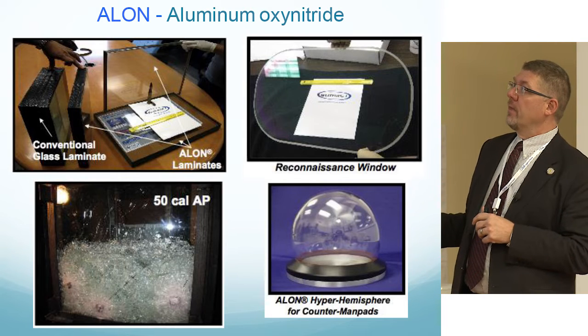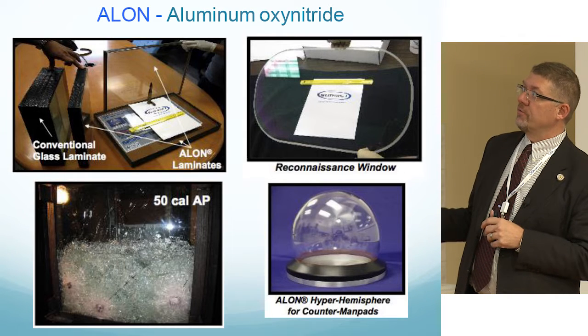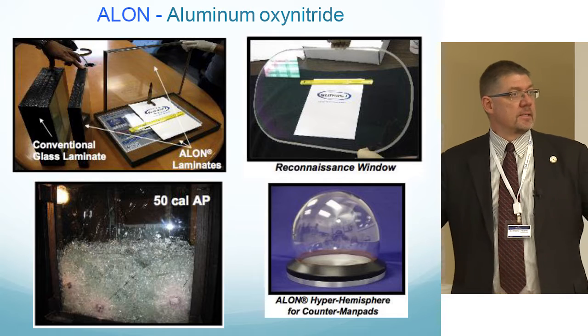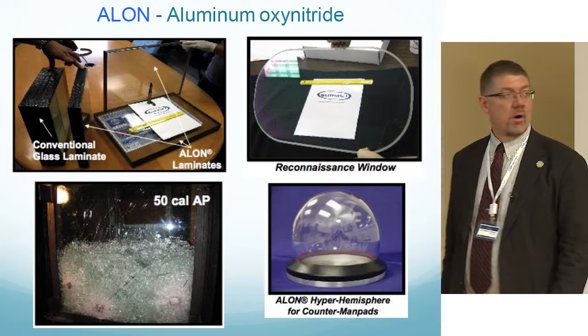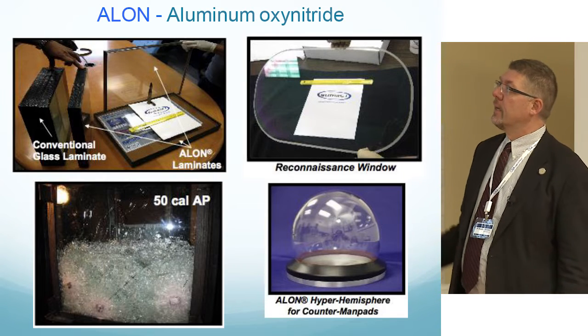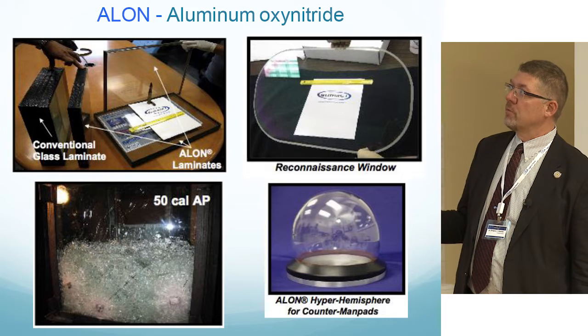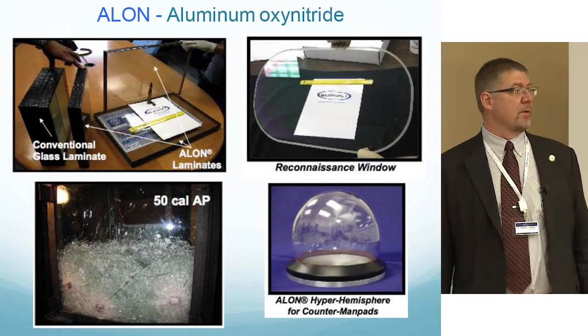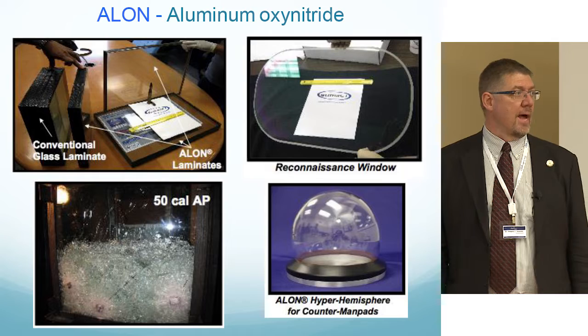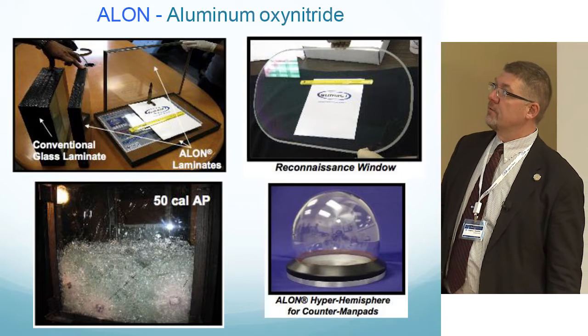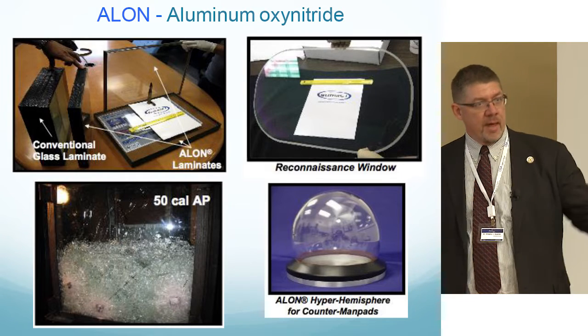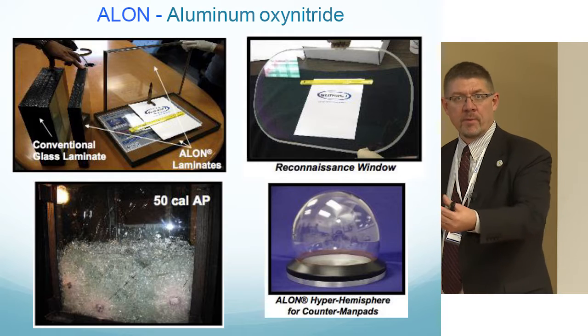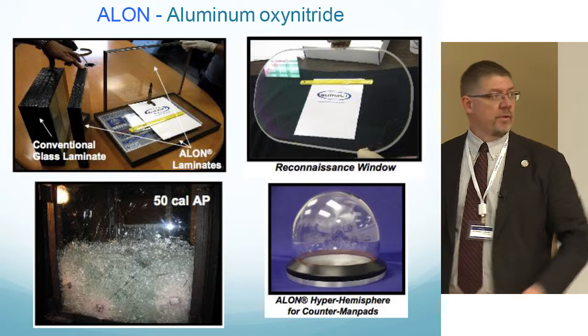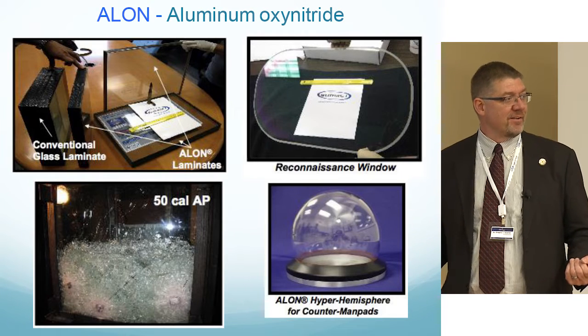Here's one of the ALON laminated windows. This is a regular window that comes out of an armored car or an armored truck. This weighs on the order of about 75 pounds, just with regular glass with laminates between it. This is about 14 pounds. So if you're sitting in that armored car and you're driving, chauffeuring somebody around, you're not going to be able to roll these windows down to get air into the vehicle.